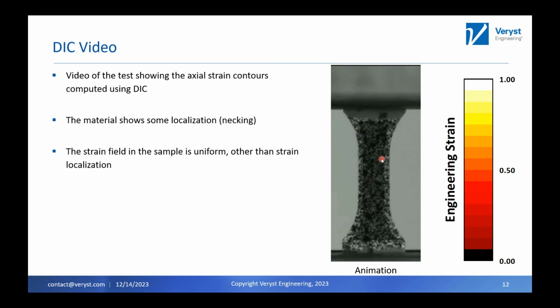The test that you're seeing here is a cyclic test, so that's why you see a pause here. But you also see in the background down here, there's a speckle pattern. That's a random black and white spray paint that we put on the surface, and that's what the DIC needs.